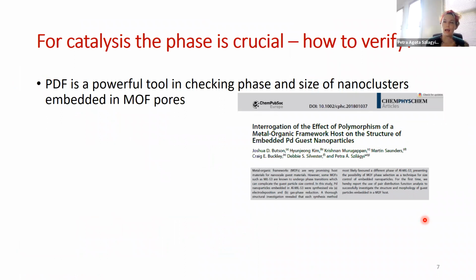And so at this size regime, once again, I would just like to come back to this typical pore size regime for frameworks, between 0.5 and 3 nanometers, nanoscience really starts to kick in, and we would start to determine the properties of the particles to some extent by the particle size rather than by the constitution of the particle. And I think one of the very interesting questions, and also very relevant for catalysis, is to what extent the atomistic structure of the bulk crystallite can be preserved for such small nanoclusters.